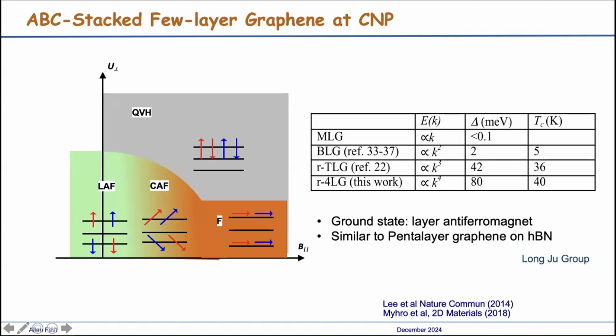And if you apply a large displacement field, you push all the electrons into one layer, either the top or bottom layer. This will give you a quantum valley Hall state. Of course, we know that recently a similar layer antiferromagnetic state at charge neutrality has been observed in graphene on hBN, by Long Ju's group, for example. And of course now also the quantum anomalous Hall state, and all that very interesting stuff.